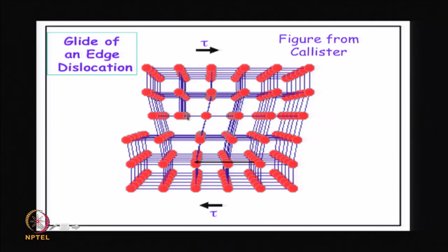For this dislocation to move one step, you can see that there are no bonds from here, the lower half of the plane is missing, and we have a continuous plane here, but there is some distortion in the bonds to accommodate this extra half plane. Now, if this set of bonds breaks here, where I am pointing the arrow, and connects with this extra half plane, then this extra half plane finds a partner below and becomes a continuous plane, of course a slightly distorted one.